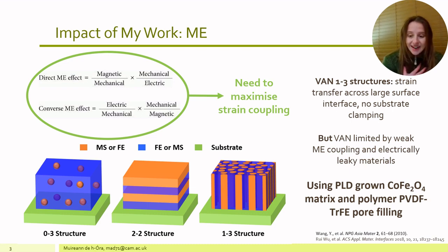So what I've been working on is using a PLD grown cobalt ferrite matrix and then filling the pores of that matrix with the polymer PVDF-TrFE to enhance the strain transfer and lower the leakage. So that's one element of my work.